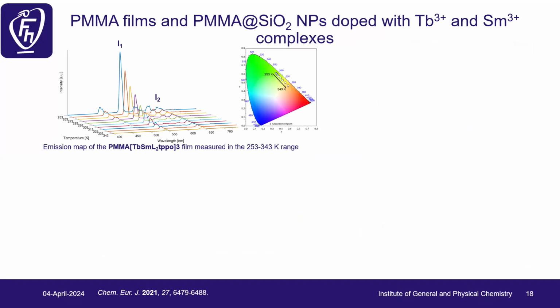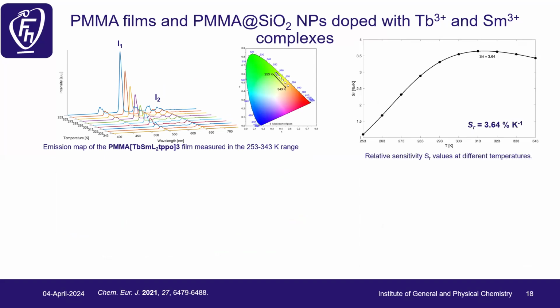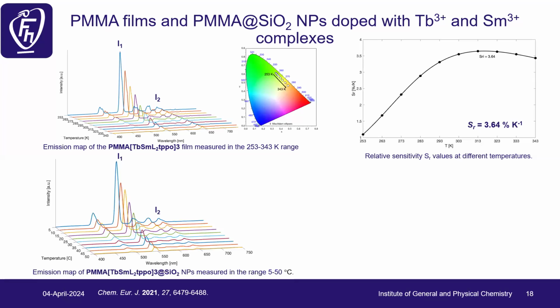Also, we have now changed from green to orange-reddish, and we got 3.64% at 313 kelvins, which is an increase of almost 1.3% compared to the first generation of our temperature sensor based on terbium samarium, which is good. And we can even try to make it better.